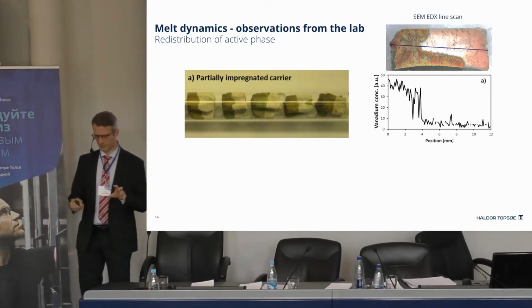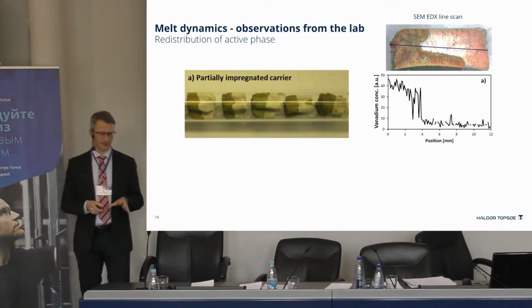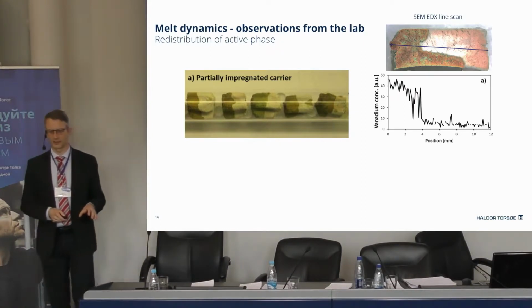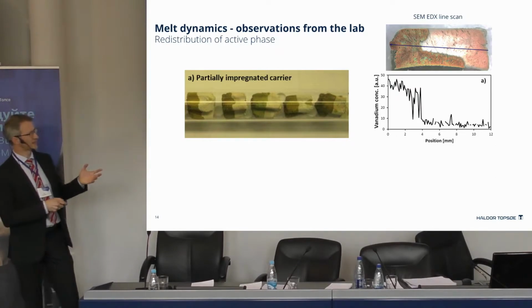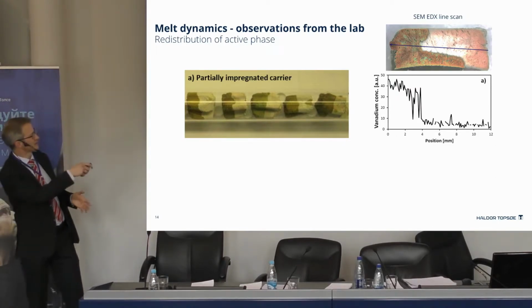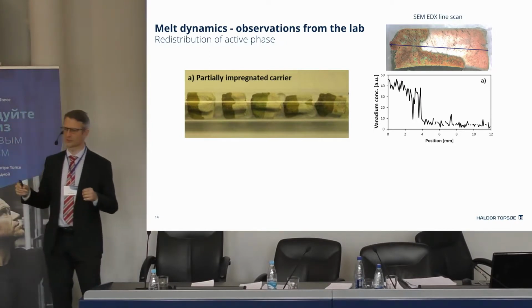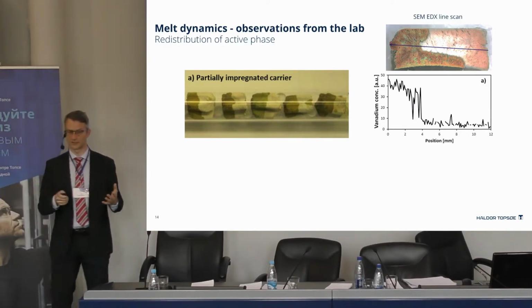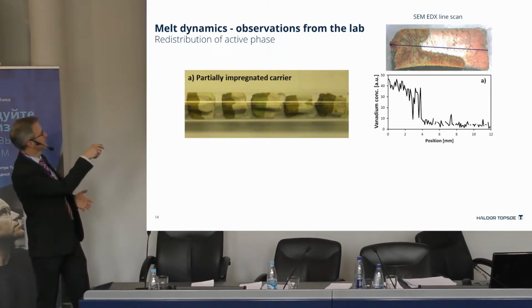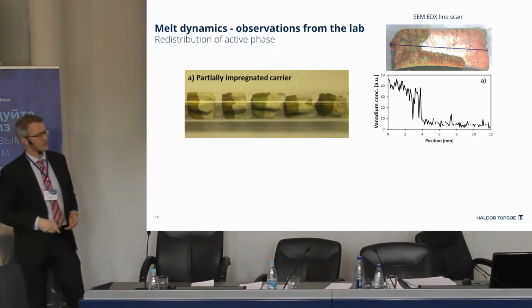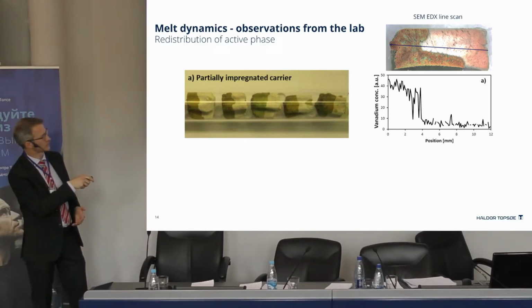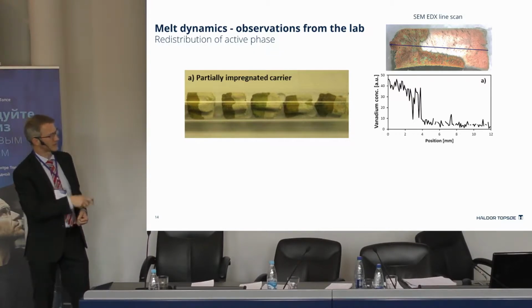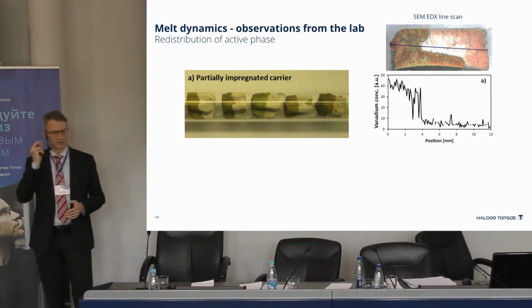First, let's take it on the lab scale and see what happens actually. Here we've done a simple experiment. We have made a silica carrier that is white. This is what you see, the white part of these pellets. And then we have impregnated partially with the active phase, which is yellow. So you can see here, this is impregnated, this is not. And if we make a line scan, you can see the colors here, but you can also see that we have vanadium in this part, and in the other part, this is effectively zero.